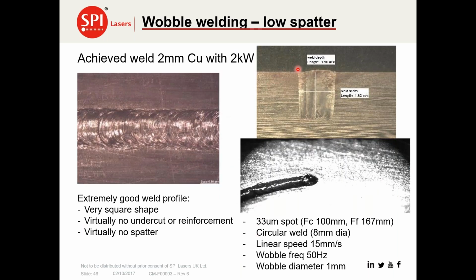Again, this is another image, actually it's pretty similar, but what you can see here is a very clean weld. Unfortunately, in these kind of events, we can't use video because the transmission is poor, but this is a video that shows the oscillation where it goes round and round. You can watch the spatter. If we get the oscillation parameters right in terms of the linear speed, the wobble frequency and the wobble diameter for a particular material combination, we can dramatically reduce the spatter generation. And there's virtually no undercut. It's flat, with very little reinforcement.